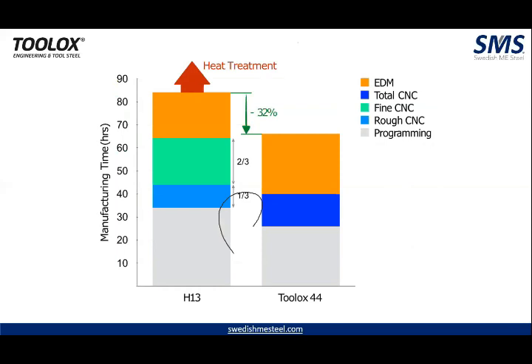You might have heard about pre-hardened P20 grade material, but Toolox 44, you can simply say, is a pre-hardened version of both H13 as well as D2. With a normal annealed condition H13, you take it, you do all the rough CNC, fine CNC. Again after that you need to heat treat it. Again you need to bring back the metal and do all the correction. Again you need to do the programming. That's not the case with Toolox 44. It is delivered to you at 45 HRC. So there is only one set of programming, one set of CNC, and one EDM.